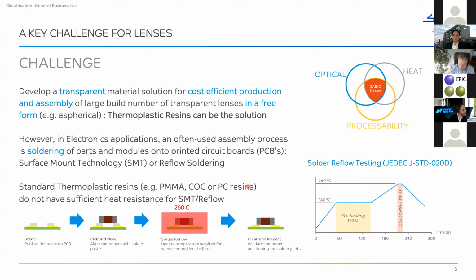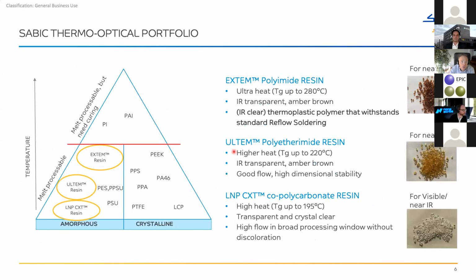Within SABIC, we have Extem, and again, this is the top of the pyramid I just showed a few pages ago. Extem is a thermoplastic polyimide resin with a Tg up to 280 degrees Celsius. And it does withstand reflow soldering, right? Because the Tg is 20 degrees higher than the reflow solder temperature.